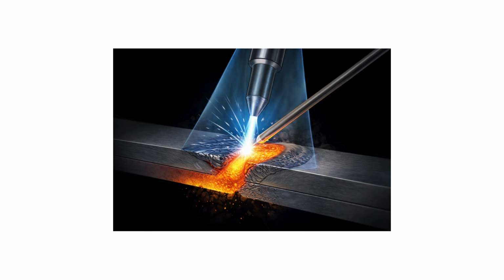So how does TIG welding actually work? When you strike an arc between the tungsten electrode and the workpiece, temperatures reach over 11,000 degrees Fahrenheit. This intense heat creates a molten weld pool on the base metal. As you move the torch along the joint, you manually feed the filler rod into this pool. The filler melts and fuses with the base metal, creating the weld bead. Meanwhile, the inert shielding gas flows through the torch and blankets the entire weld area. This is crucial, it prevents oxygen and nitrogen from the air from contaminating the molten metal, which would create weak, porous welds.